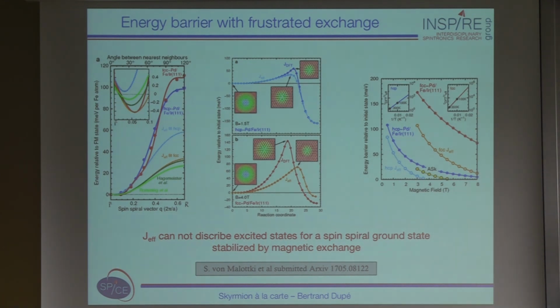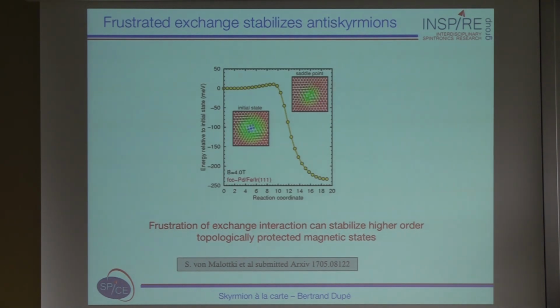So now the bonus of this frustration of exchange is that you actually stabilize the anti-skyrmion. So it's the same picture as I showed you before, and you see here that it has a very small energy barrier, so we can actually play around with the anti-skyrmion in this system for reasonable magnetic field.